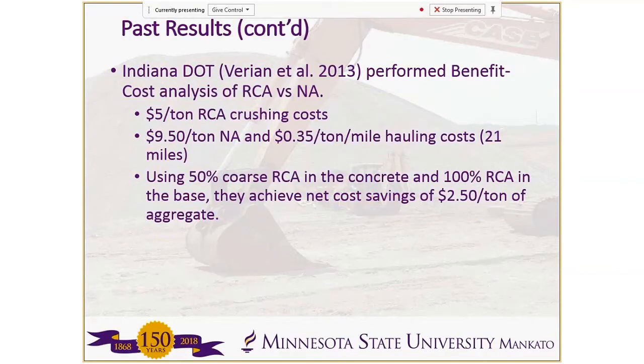Indiana DOT also performed a benefit cost analysis looking at recycled concrete versus natural aggregates. Some of the assumptions that they had in their analysis, they assumed $5 per ton for the RCA crushing costs, $9.50 for the natural aggregates, and 35 cents per ton per mile for the hauling cost. So using these scenarios, they came up with a net cost savings of $2.50 per ton of aggregate when using the RCA versus the natural aggregates.